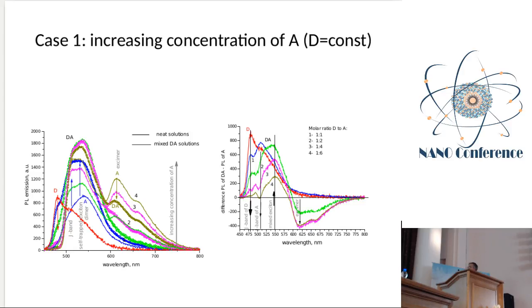So in this picture, we see that this enhancement is due to the quenching of the donor J aggregates here, and then at high concentration, we observe also quenching of J aggregates of the acceptor. And also we observe less contribution of excimer in the mixed solution, as I showed you before.